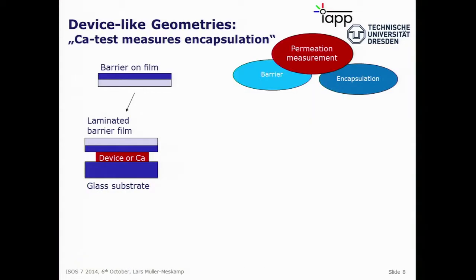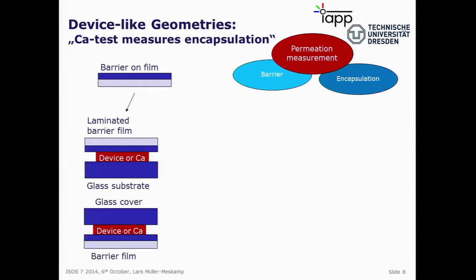Okay, I will talk a bit about why I like the calcium test so much. It's because it can measure in a device-like geometry the encapsulation. You have a barrier film with a barrier value, but when you use a calcium test, usually you put the calcium or the device on the glass, and then you laminate the barrier on top and measure. So that's a very device-like setting, or you can flip it around, and that's what we usually do.